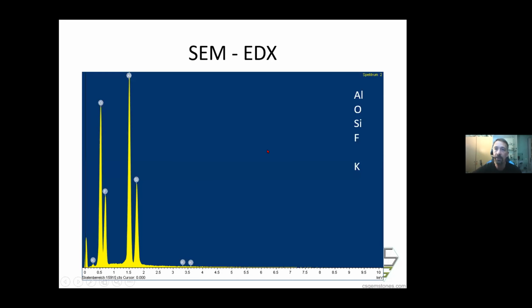This is how it looks. So you get some peaks and you get some elements. We have oxygen, we have fluorine, we have aluminum, silicon, a little bit of potassium here. And with this wonderful technique, this energy dispersive X-ray spectroscopy, you can determine the content of fluorine versus the oxygen. And this is the first wonderful difference where you can differentiate different topaz localities, or at least the growth, if it's a hydrothermal growth or if it's pegmatite. And this gives you the content of fluorine, which is not easily accessible by many other techniques.